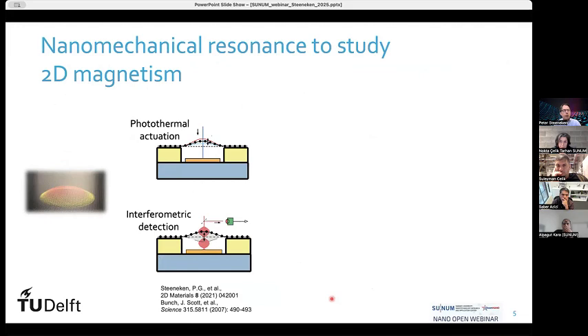And how do we do it? You cannot easily contact something, so we were looking for contactless methods to actually study the nanomechanical resonances. For that, we use a technique where we use a blue laser, which is heating the membrane a little bit, whereas the laser power is varying in time. As a consequence, the membrane heats up and cools down in time and expands and contracts. As a result of that, it starts moving. And if you do it at the right frequency, you can also bring it into mechanical resonance.